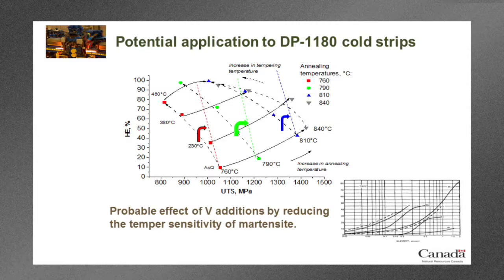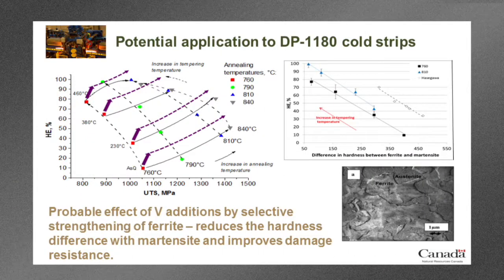That's not the only benefit that we would have from the vanadium. There is this other property, which I spent some time describing in the TRIP steel, where we have selective strengthening of the ferrite. If you remember, this microstructure here is actually a dual phase microstructure, and we strengthened the ferrite and we didn't change the martensite at all. So now, let's assume that we can do the same thing in this dual phase steel. What would happen? First thing is that we would have an overall increase in the ultimate tensile strength at the same composition, same carbon level, I should say, because we strengthened the softest phase. So we would have a shift along this axis here.